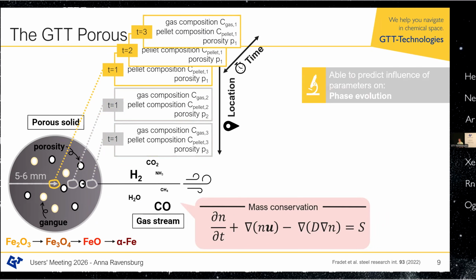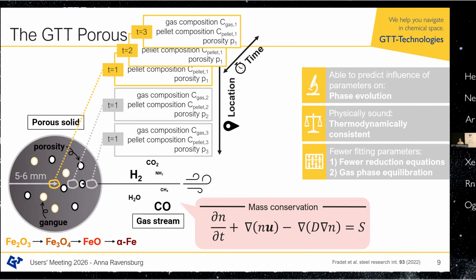What this model can do is that it is able to predict the microstructure, because more phases can be present at the same time, because we have this phase composition inside the mass conservation equation. We have made it thermodynamically consistent, which was one of the problems with the porous solid model as proposed by Frade et al., by taking ChemApp into this model and making it evaluate the driving force. And what was most important to us was that we have drastically reduced the amount of fitting parameters, because this was one of the big problems, that you always need experimental data to validate your model in some way. And if you have too many fitting parameters, it's quite easy to fit the experimental data. If it's physically sound, it's not really a question then.